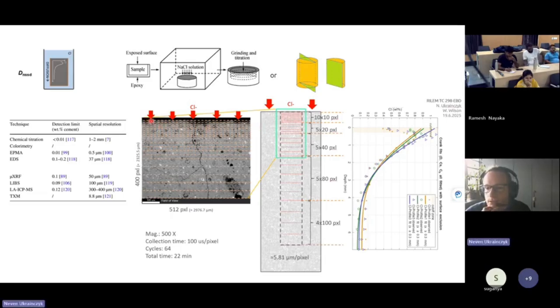Yeah, it's quite tedious to do it because we wanted to automatize it, like with image analysis tools, but the problem is that the EDAX software is fitting the EDX profile to measure the composition. It can only be done in the software, so it's difficult to automatize. We can get the composition of each pixel, but that one pixel is not enough because it's very low resolution. You need a statistical average, a lot of pixels, to get a good EDS signal that you can fit to get a good concentration composition.